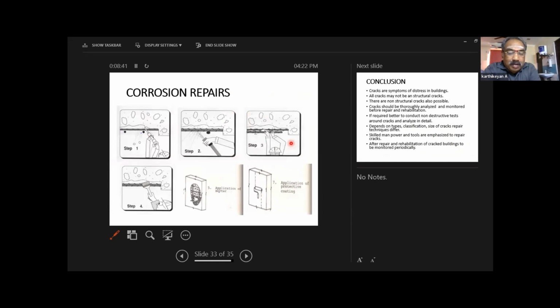And corrosion repair. We have seen elaborately how the rod gets corroded. When the rod gets corroded, the concrete surface cracks. People can simply ask a mason to remove the corroded surface and then again replaster or reconcrete. Within a few months, the corrosion occurs again and it continuously cracks. So how to avoid it? Step number one, you have to remove the entire cover concrete, okay, and then expose your steel rods, and then remove the corrosion by sandblasting or emery paper or corrosion removal chemicals, so that there is no corrosion on the steel.